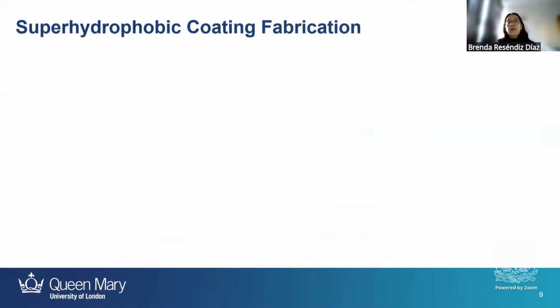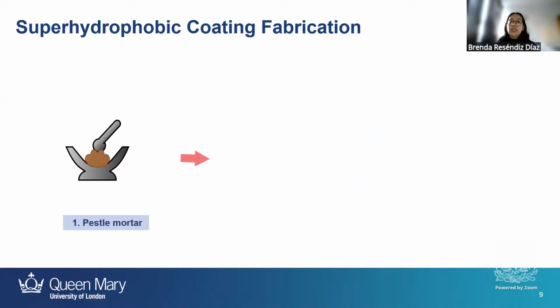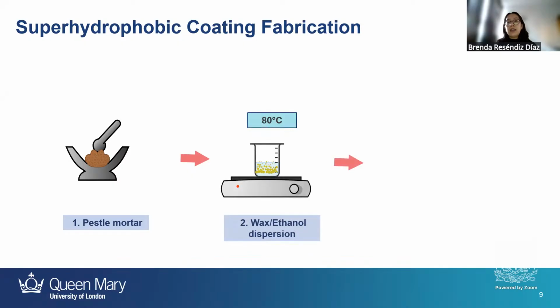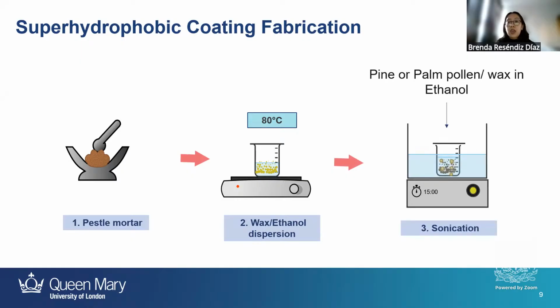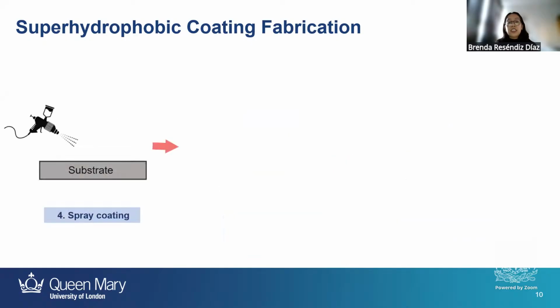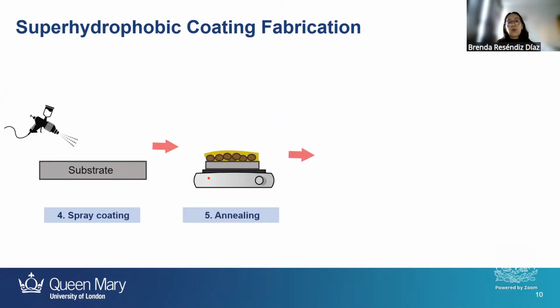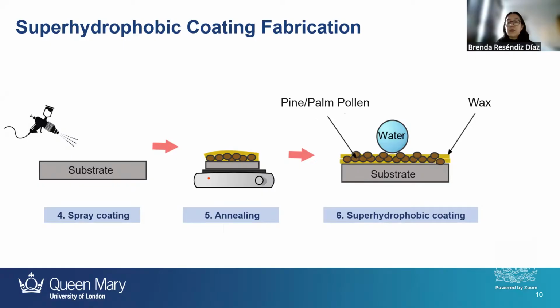So for the superhydrophobic fabrication, what I do first is take that sample and use a pestle and mortar to make a fine powder. And then I mix wax and ethanol to make a proper dispersion. And then I mix pine or palm pollen in ethanol. And then I sonicate it for 15 minutes to have a more stable dispersion. I use spray coating as my main technique, and I anneal the wax to cover all the features of the pollen, and then we obtain a superhydrophobic coating.